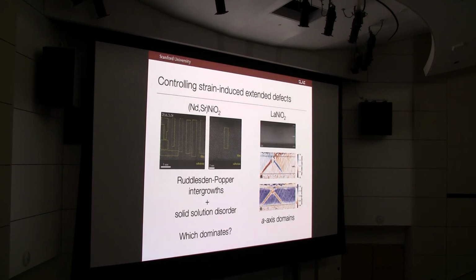What's interesting is that when we go to a larger lanthanum nickelate, it's slightly more comfortable on our substrate, and we can largely eliminate these sorts of extended defects. We actually find a different one. I don't know if your eyes can see these little diagonal slants here, and if you look at this in terms of a relative rotation or the ratio of the in and out of plane lattice parameters, the simple story is this is like the material wanting to go from planes in this direction, rotating up and back down. So this is kind of the dance in our lab: we've gotten rid of some defects, we're near the instability to other ones, and the question is, can we really eliminate this? I think we're very close now to getting towards what we would call the intrinsic behavior.